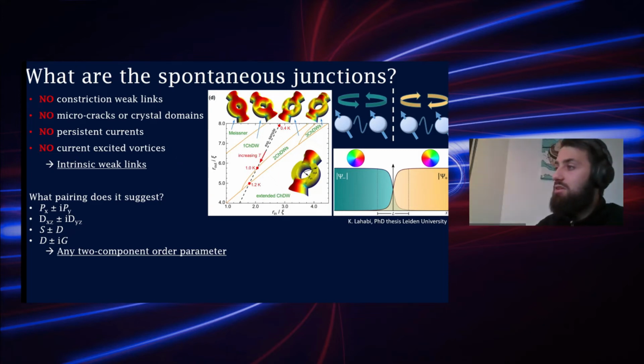So this can be modeled like this, for example. In yellow there is one of the components. Then at the domain wall, one of the components decreases in magnitude, so the wave function of one of the components, and the other is increasing. However, locally, the condensate is suppressed, and this acts as a Josephson junction between, for example, two chiralities in the p-wave picture or two chiralities in the d-wave picture.